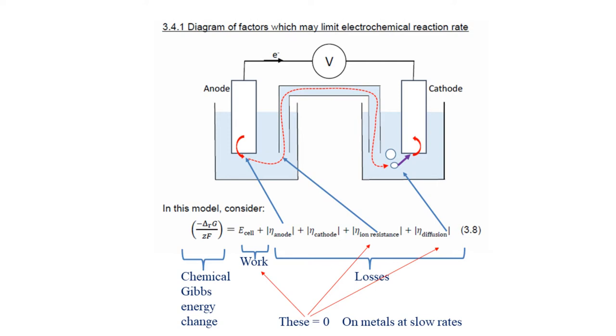So I'm going to consider how fast this corrosion process happens, given that all of the chemical Gibbs energy change of the process, of the metal dissolving and hydrogen being discharged, all of this is turned into driving force for corrosion. So I'm not draining any energy from this system, making it work as a battery. I'm considering zero energy lost by heat generation as ion resistance in the solution, and zero energy drawn by electronic resistance. I'm only considering what voltage is produced from my Gibbs energy change, and what voltage is lost because of the anode process itself, that's the metal dissolving, and the cathode process itself.